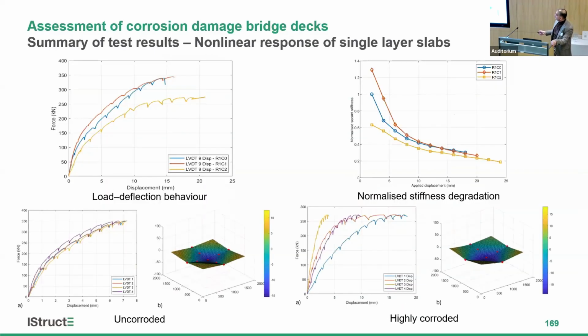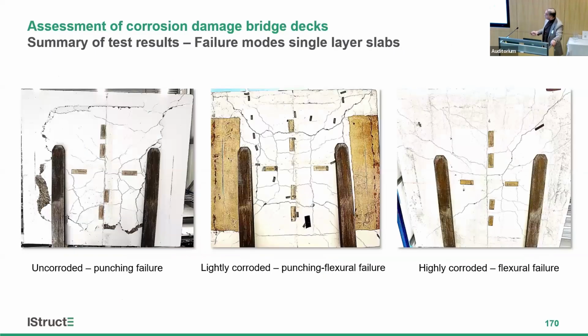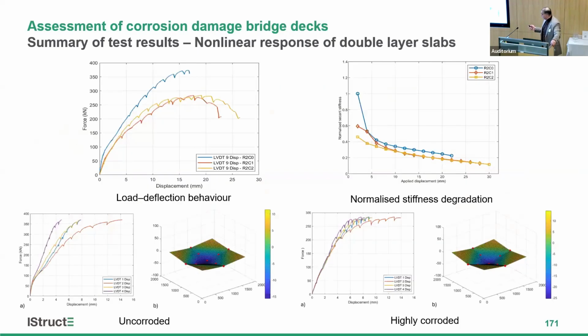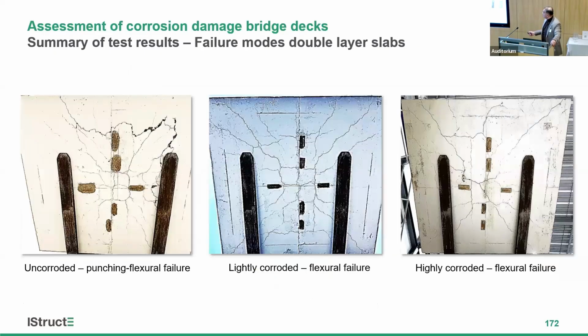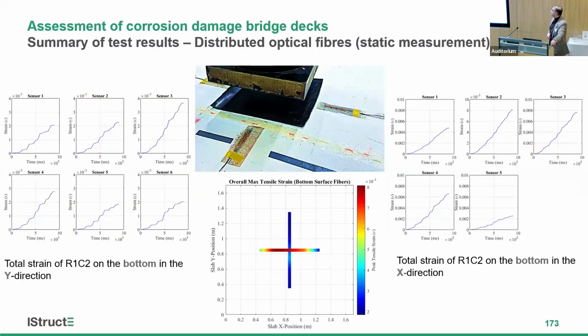And this shows that the failure mechanism is essentially changing from punching to flexure failure. And we can see the crack pattern. So you see single layer is a punching failure, comes to a punching flexure, and then finally comes to a flexure as corrosion is increasing. The double layer is similar. So we get a bit of punching, and then it's a punching flexure, and then it goes towards fully flexure behavior, and the deformations are quite unsymmetrical. And again, this is the crack pattern.